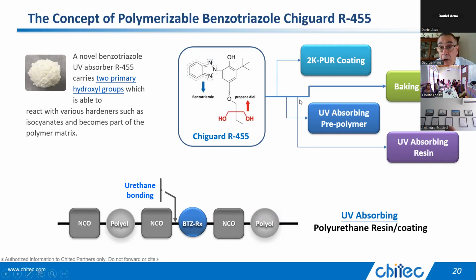Now, I said in a 2K iso, you don't have to have it cure in. You can actually polymerize it into a prepolymer. So a polyurethane dispersion and a waterborne coating, we've done that several times. It works great. It reacts in with a melamine coating. Usually that's done during cure. So whether you react it in ahead of time into your polymer network for your resins or have it cure in, either way, it reacts in really well and gives you an outstanding performance.